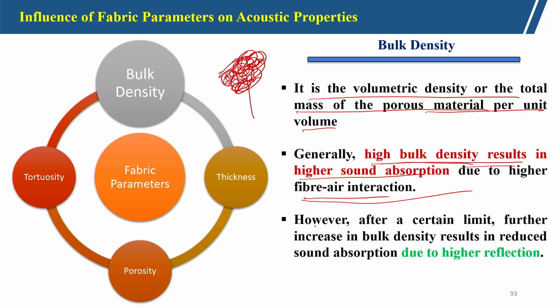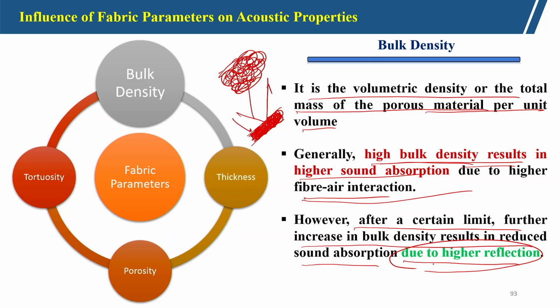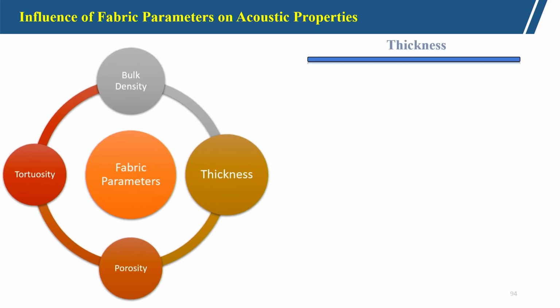But if we keep on increasing the bulk density, after a certain limit, a further increase in bulk density results in reduction in absorption due to higher reflection. If the surface is very compact, because we have increased the bulk density a great deal, there will be very few pores within the structure. So, sound will not be able to penetrate inside, it will simply reflect back. Higher reflection will be there, so sound absorption will be less, reduced absorption. So, there is an optimum range.